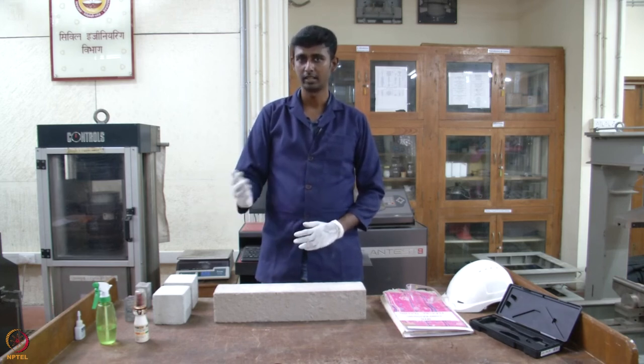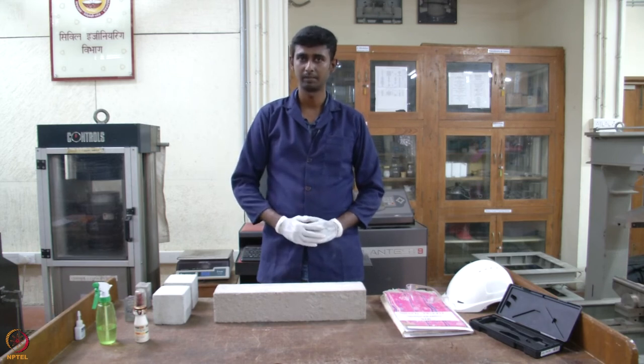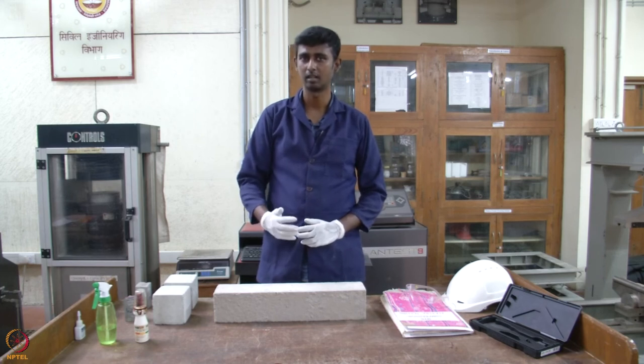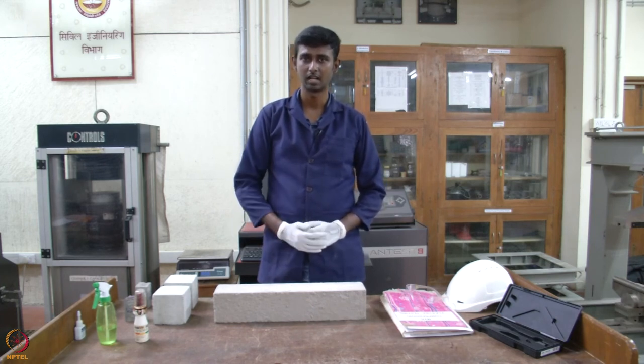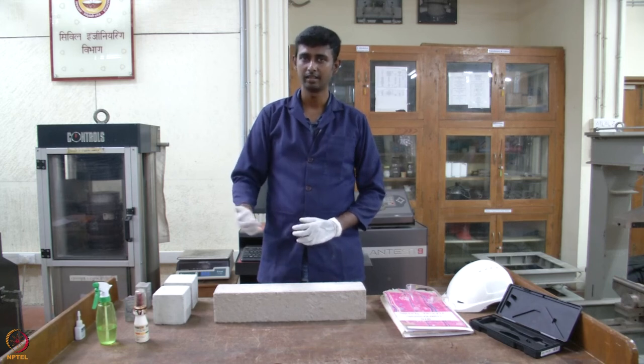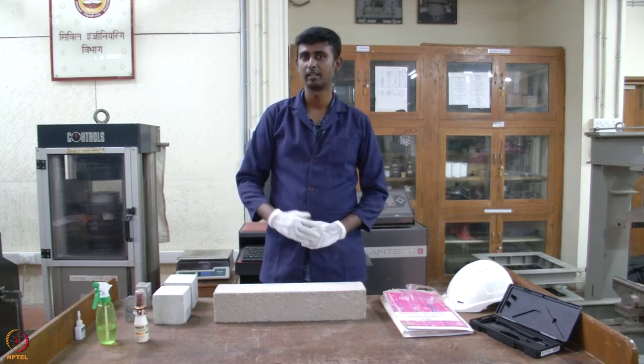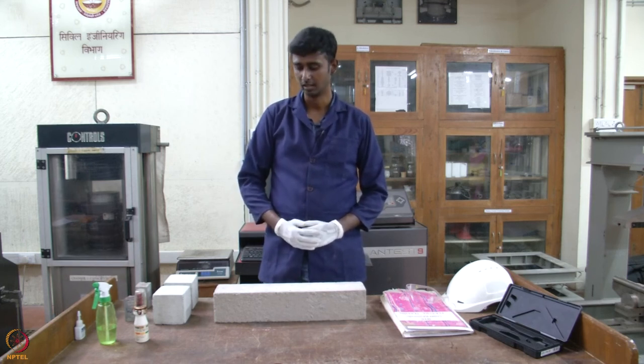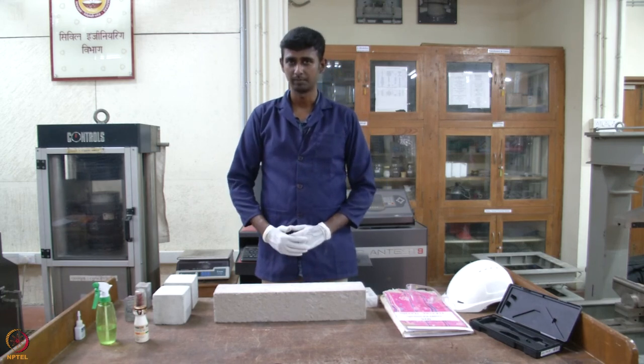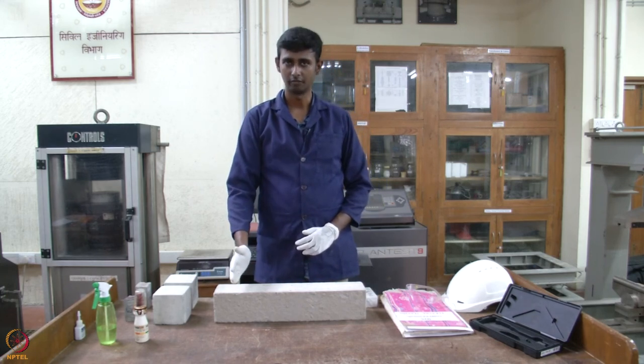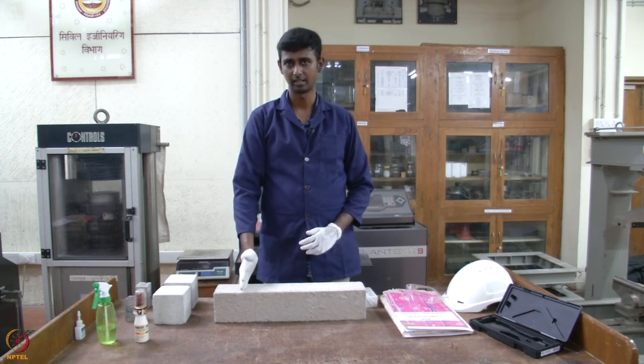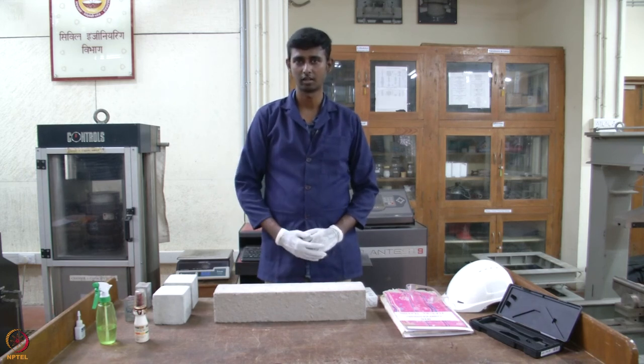Using Tuutti's model, we will fit the mean carbonation depth at these three or four different ages, and then calculate the carbonation coefficient of this accelerated carbonation test. Based upon the relationship between the natural and the accelerated carbonation tests, we will derive the natural carbonation coefficient, and then we can substitute that natural carbonation coefficient in Tuutti's model to calculate the service life of the concrete system under carbonation-induced corrosion. Similarly, for concrete specimens, we can take slices at each time interval using shear cutters, and then do the measurements as I did for the mortar specimens.